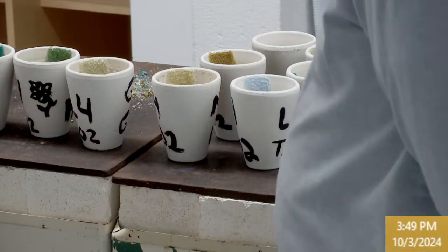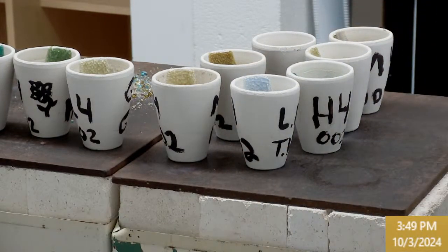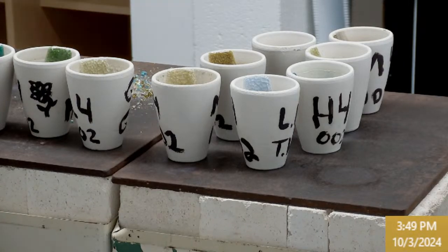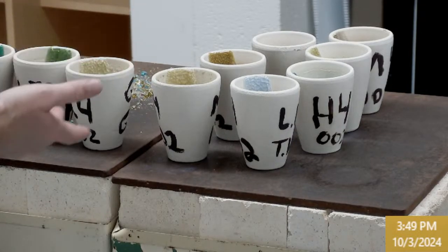The glass is shrinking at a different rate than the crucible, but as the glass hardens up, it can no longer give like it could when it was hot. As it's loading up that thin layer, it doesn't have the shape to pull against and stabilize because it's a surface film. That's when you get all those little cracks and crazes. At the beginning, you can literally look at the crucible and hear it, and there'll be an immediate line that shows up in the glass. But these are now obviously mostly stabilized.